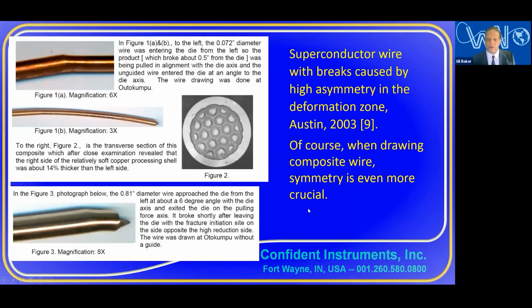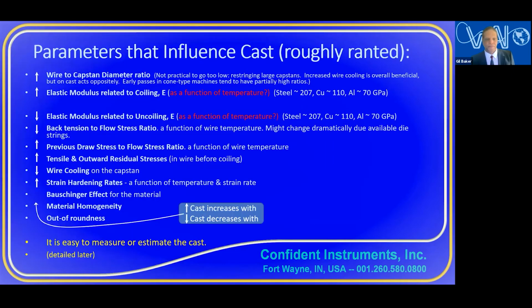Here's some examples from an article written by Austin on superconductor wire. He was having problems with wire breaks, and he believes that the asymmetry in the deformation zone shown here caused those breaks. Again, in drawing superconductor wire, you're very concerned about the shape of the internal product. So there's another reason you always want to improve your die alignment.